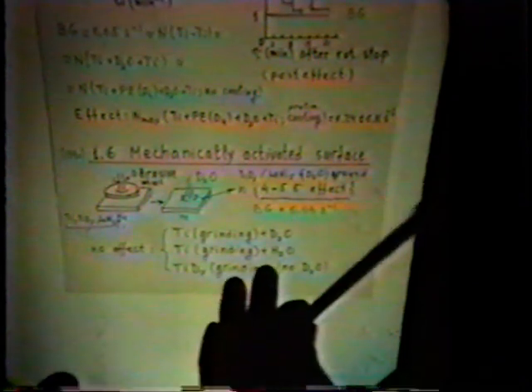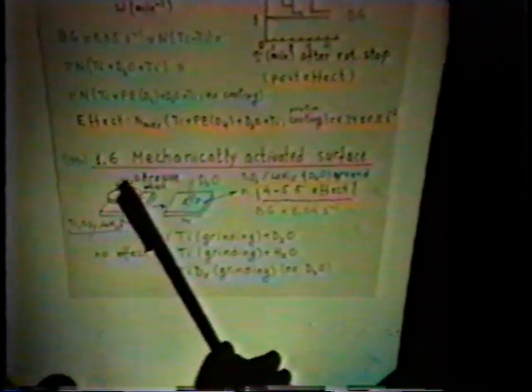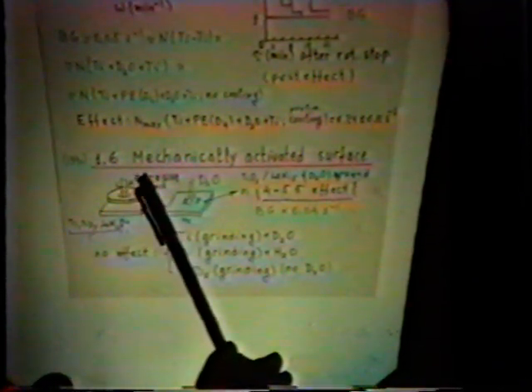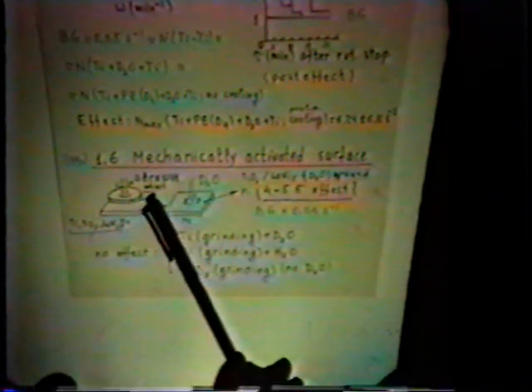The next experiment of this group was connected with measurement of neutrons from a mechanically activated surface. Deuterated titanium and lanthanum nickel-5 were ground with abrasive glue and then moistened with heavy water. And a 4 to 5 sigma effect in neutron emission was observed above the background level. However, they didn't observe any excess for the following combinations.